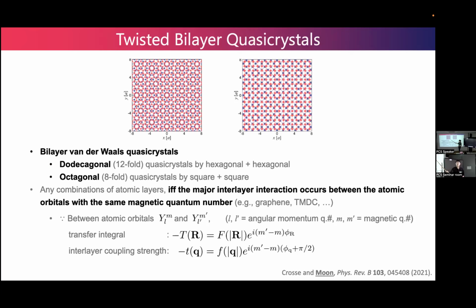And yeah, we can make the quasicrystal by stacking hexagonal layers in a 30-degree configuration, or 8-fold rotational symmetry by stacking square lattices at 45 degrees. And then we can get the resonant state if and only if the major interaction occurs between the atomic orbitals with the same magnetic quantum number.